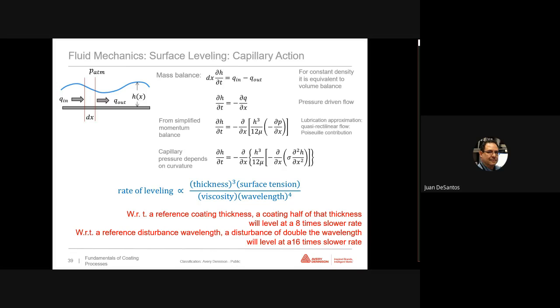This means that with respect to a reference coating thickness, a coating of half that thickness will level at 8 times lower rate. Also, with respect to a reference disturbance wavelength, another disturbance of double the wavelength will level at 16 times lower rate. So, short waves level much faster than long waves.